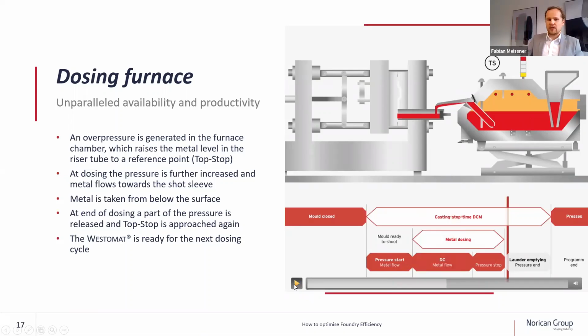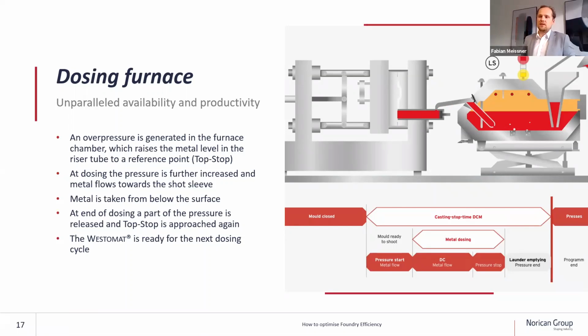And then once we have the right amount of material in the shot sleeve, we stop the dosing process, and we take out the pressure. The pressure is released, and that's it. So that's the principle of how we are dosing aluminum with our Westomat into the shot sleeve, and it's compared, for example, to a holding furnace with a ladle. It has many advantages.